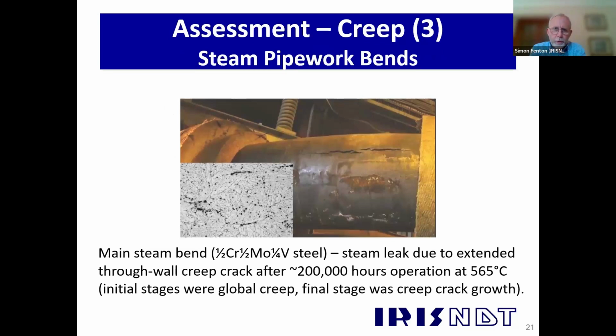So in terms of parent material, this is something we don't want to see, obviously. This is a 600 millimeter long creep crack in a main steam pipework bend on a UK coal-fired site. The site's now closed. So this was discovered in 2006. The plant had been in operation for about 200,000 hours, operating at 565 degrees C. So it's a low alloy steel, 0.5% chrome, half moly, quarter vanadium. The design life was 150,000 hours, so it's well past its design life.